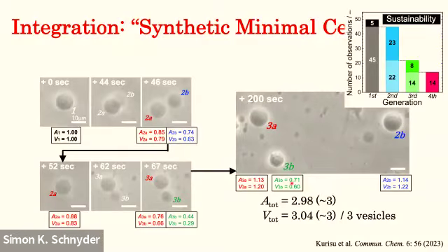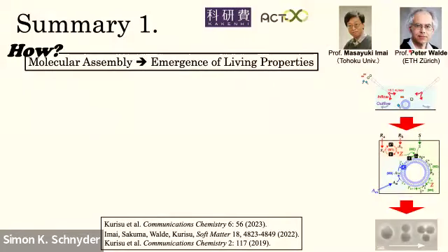I carried out 50 experiments by this. Here, 45 initial mother vesicles showed first division, and then 22 of them showed another division, and then 14 of the granddaughter vesicles showed another division like this. So sustainability becomes less and less, but I think anyway, based on such a strategy, I constructed the reproduction of a vesicle system coupled with the chemical reaction network.